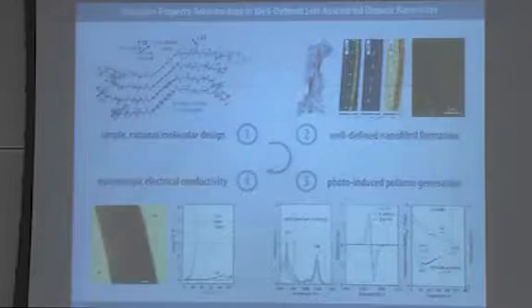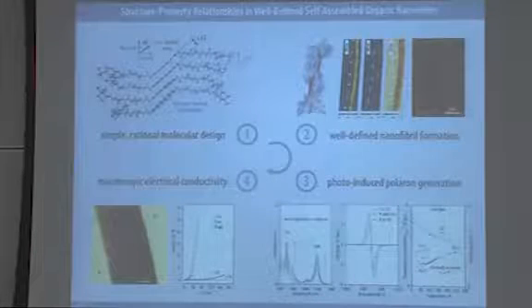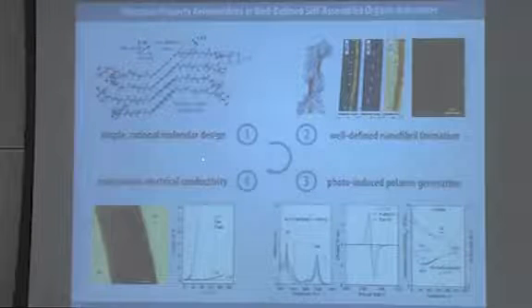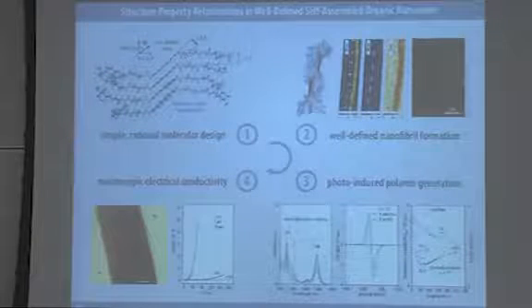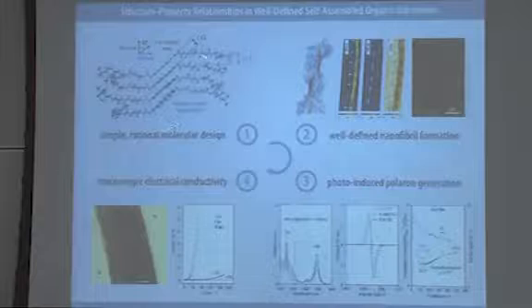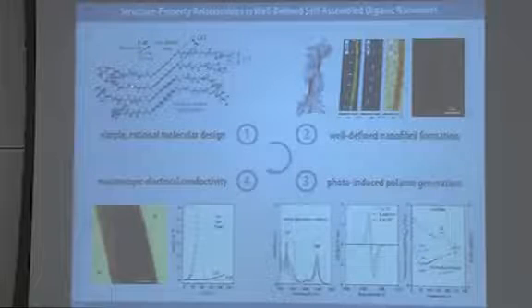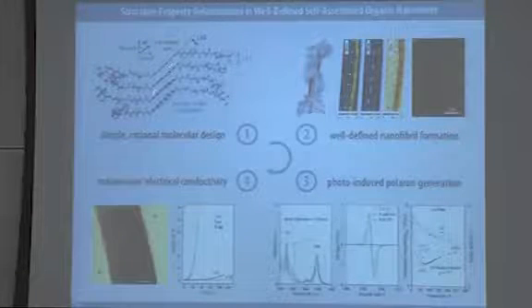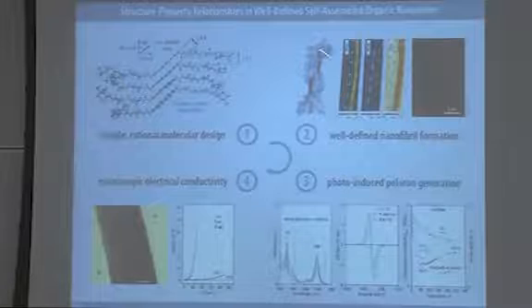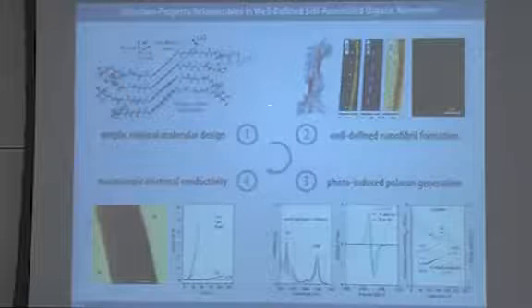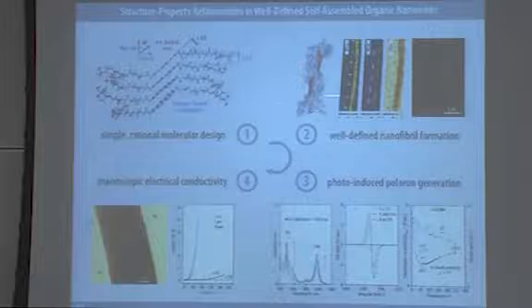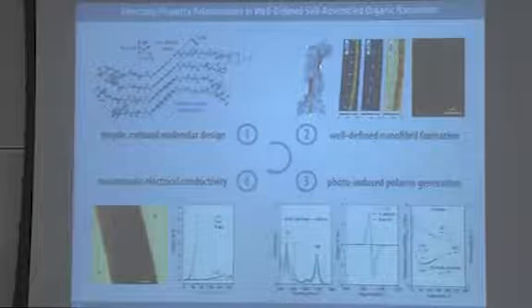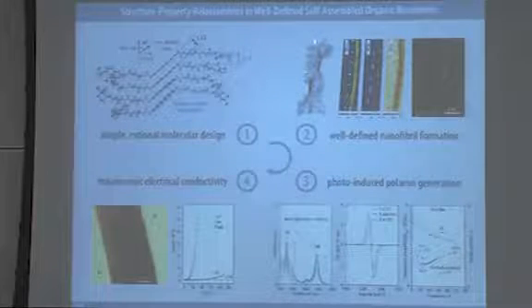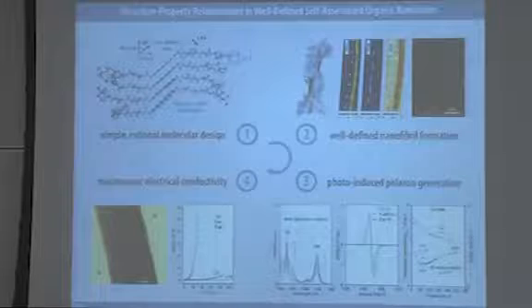So I hope that indeed I've been able to make the full circle, starting with synthesis and the molecular parameters needed in order to assemble molecules by a combination of hydrogen bonding and pi-pi stacking, so that you obtain well-defined nanofibrils with defined lateral dimensions, and more importantly, a very tight stacking of a single stack of pi conjugated molecules at their core.